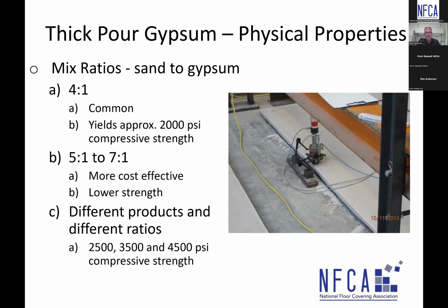Got a question: if gypsum can be poured, you do not need a primer, is that correct? The thick pour gypsums are very common. It's very common to have a primer. The engineered gypsums that we'll talk about in a little bit, some of them require a primer, others may not. But the thick pour gypsums, the 3/4 inch and thicker products, typically do require a primer. And a water droplet test is what you would apply to determine whether you've got acceptable absorbency or not.